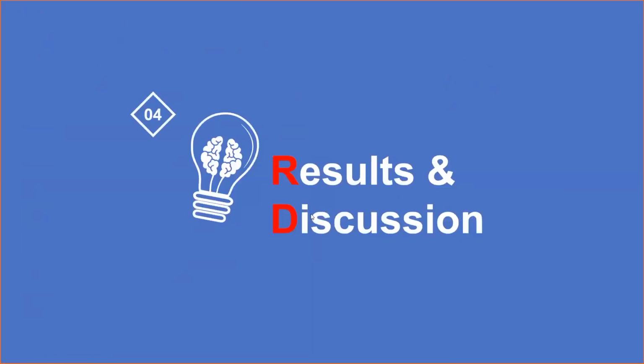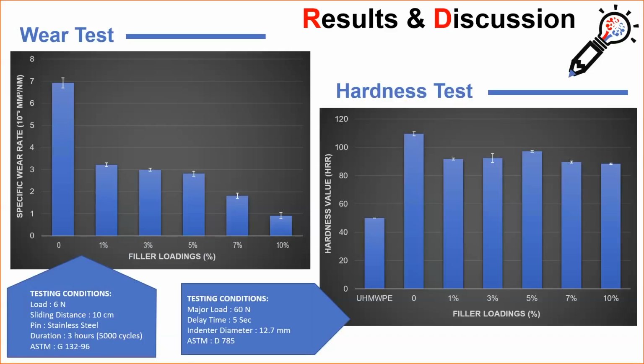Okay, for the results and discussion. This is the plotted graph of the wear test result and hardness test result. The wear test was conducted at 6 Newton load and 10 cm sliding distance for 3 hours using a stainless steel pin according to ASTM G132-96. The result of the specific wear rate was plotted against increasing percentage of filler loading. As can be seen from the graph, the specific wear rate of neat epoxy is about 7 times 10 to the power of negative 5 millimeter cubed per Newton meter.